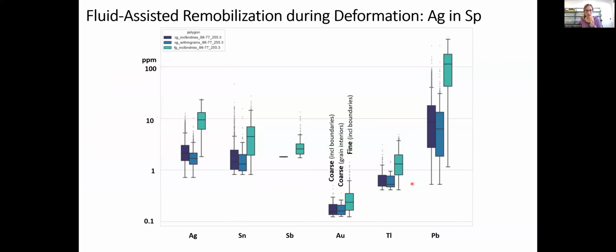And again, we can quantify that. And here you can see with silver, much higher in the fine-grained recrystallized areas. Same for tin and antimony, kind of with gold, whole bunch of elements. And that suggests that all of these guys are being remobilized in the fluid phase and moving along grain boundaries.